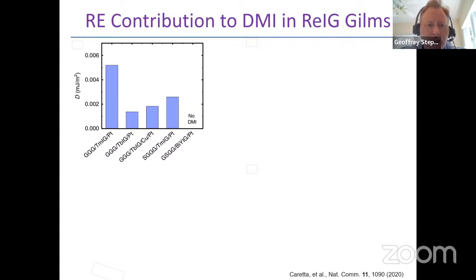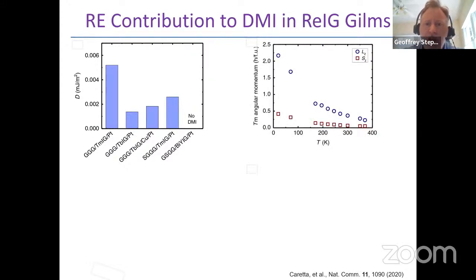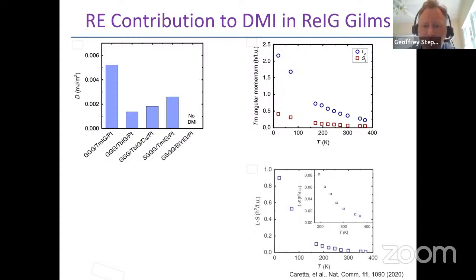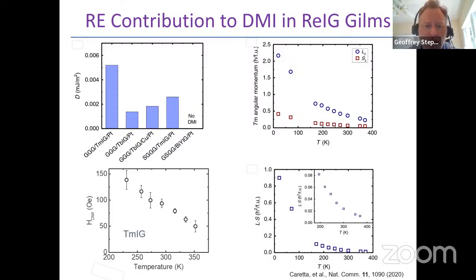Regardless of what the metal is on top, when there's a rare earth, we tend to get DMI. When there's no rare earth, we don't get a DMI. When we look at the temperature dependence, we find a very strong temperature dependence for the rare earth magnetic moment, the rare earth angular momentum, so presumably the rare earth spin orbit coupling. And when we look at the temperature dependence of the DMI, we find a very similar strong scaling of this.